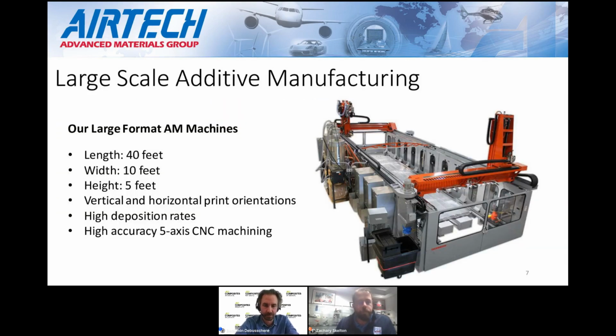So in both locations, we have two Thermwood LSAMs. So they are 40 feet by 10 feet by 5 feet build envelopes. Both gantries can cover the complete envelope of the machine. So high deposition rates, we can extrude up to 500 pounds an hour. So tools get built extremely quickly, but then post-printing, we can come back and machine to aerospace levels of finish and quality.